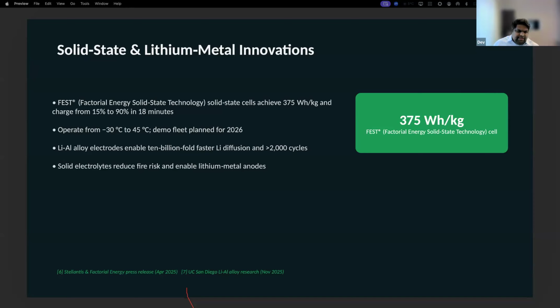The challenges are mostly about interfacial resistance, dendrite penetration, as I mentioned before, dendrites are like micro cracks within the separators, and the manufacturing scalability. So they have achieved certain chemistries which kind of fix this problem. However, they may not be able to scale it up on a commercial basis.